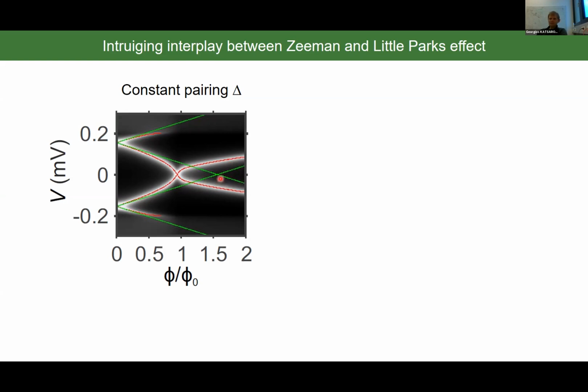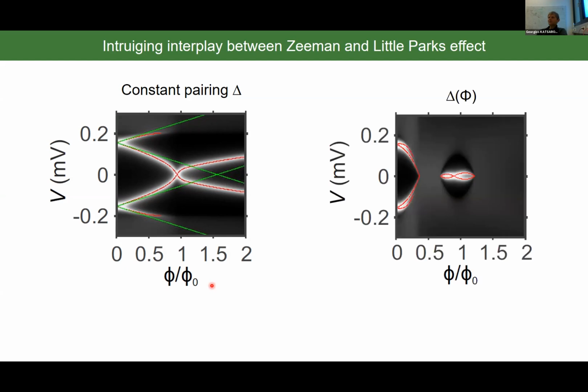So you already see that there is a deviation between the purely Zeeman regime and the superconducting Anderson model, in which you need to take into account also that now you have a coupling to the superconductor. But where everything becomes much more complex is when now you allow delta to be a function of the flux. So the picture completely changes, and actually experimentally you would not be able to understand that these were Andreev bound states.